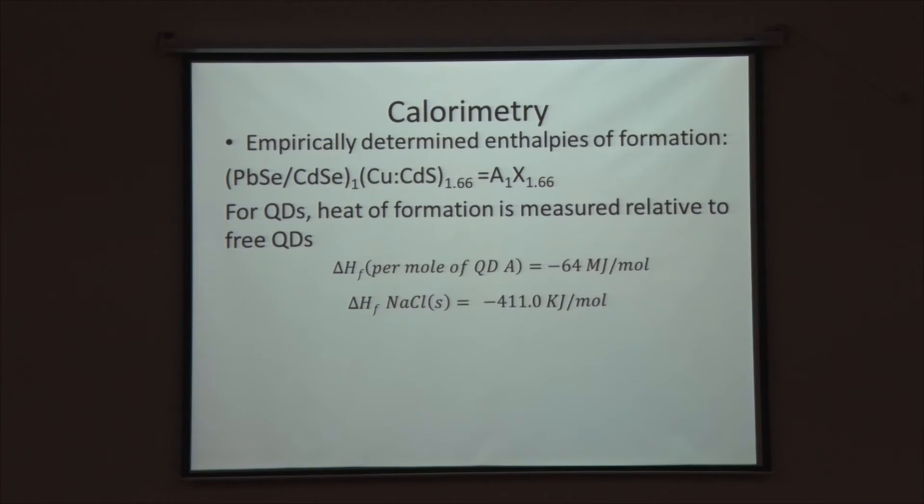While I cannot pull the quantum dots apart yet, what we did do was some basic calorimetry. We took a lead selenide cadmium selenide quantum dot which was reacted with another quantum dot. They react in a ratio of 1 to 1.66 and we tried to evaluate the heat of formation. We find that we have a heat of formation in the case of quantum dots which is 64 megajoules per mole. That is a very large number. If we think of something like sodium chloride, it is only 411 kilojoules per mole. So we are orders of magnitude above what sodium chloride does.